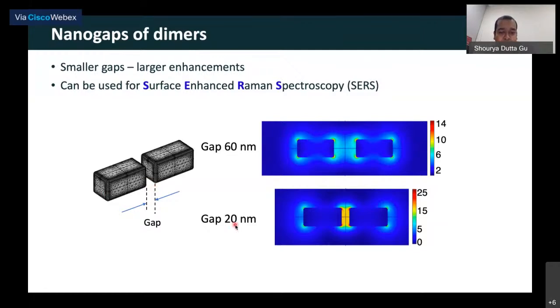Now, if I have a gap of 20 nanometers, I see that the field, which is shown by the color, so red is a higher field as compared to blue. As I reduce the gap, the field increases, right? So if I have to use it for surface enhanced Raman scattering, where the signal is proportional to E to the power 4, I would prefer a geometry which has smaller gaps as compared to larger ones, right?